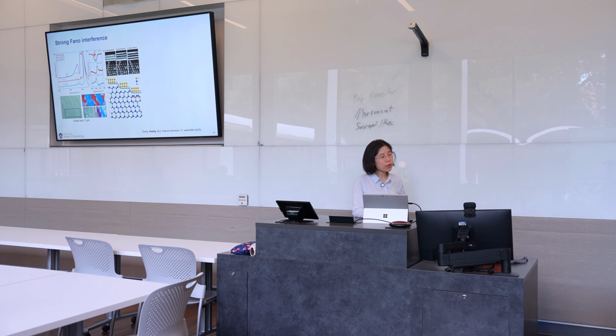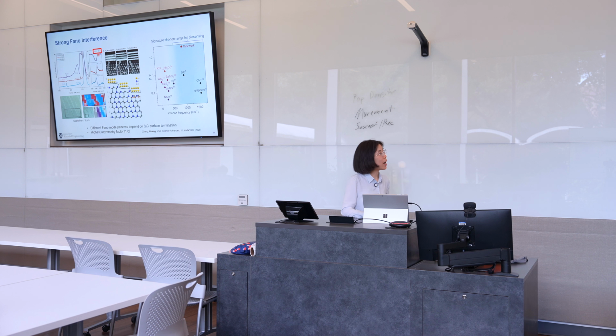But now if you look at this 1/q value, as I mentioned, the larger the 1/q, the more asymmetric the line shape is. And that means a stronger Fano interference between the discrete state and the continuum state. So here we actually have a very large 1/q. The absolute value is about 30. If you compare this with other phonon modes observed in other materials, you realize this 1/q factor is at least an order of magnitude higher than any other materials. So this is very exciting. We have a very strong Fano interference, or quantum interference, in these phonon modes.